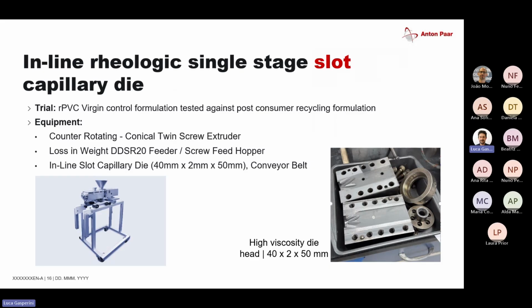Okay, here is just an example of an inline rheological measurement for PVC applications. This is what the slot capillary die looks like when it's opened up. You can see here is one hole where we can measure the temperature inside of the die, and there are two holes for the pressure transducers. There's a fixed distance. This one is one of the smaller slot capillary dies with a distance of 50 millimeters between measurements. It has a height of 2 millimeters and a channel width of around 40 millimeters.